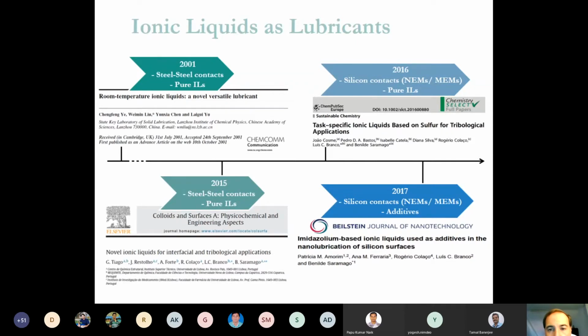This is a very huge area because silicon is crucial for many materials, and this is the nano electromechanical systems, NEMS and MEMS, a very important area in mechanical engineering. And we proved that task-specific ionic liquids based on sulfur are very interesting for tribological applications. And more recently, three years ago, we used ionic liquids only as additives, because looking at the price and the possibility of a large scale-up of this technology, we can prove that it's possible to use a small quantity of ionic liquids as an additive, in particular imidazolium-based ionic liquids,